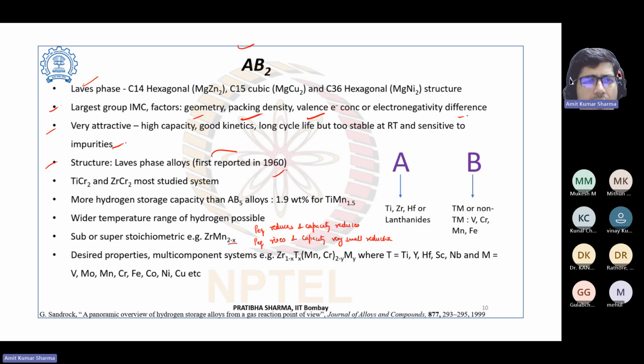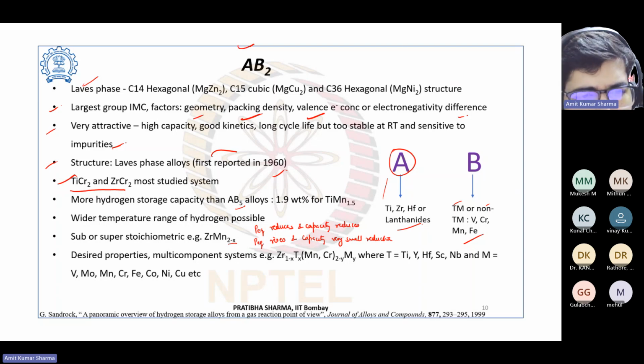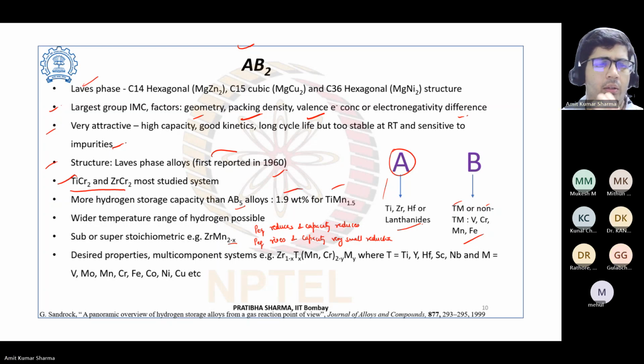It was first reported in 1960. In this category, TiCr2 and ZrCr2 are the most studied systems. Here A can be Ti, Zr, Hf or lanthanides. B is TM or non-TM. B is Cr, Mn and Fe. So more hydrogen storage capacity than AB5 alloys. In the previous one we had around 1.2 weight%, but here we can see it is 1.9 weight% for this TiMn1.5. Wider temperature range of hydrogen possible.